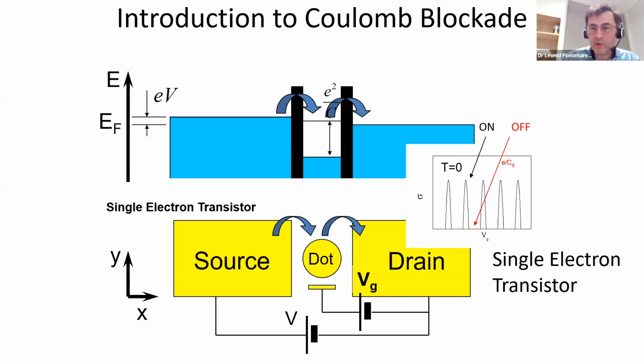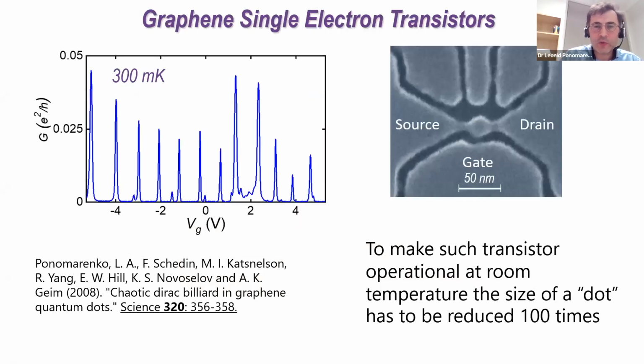It was a really, really hot topic in the 80s when these transistors were made of traditional semiconductors and metallic islands. They work only at low temperatures. So we have actually tried to do this with graphene, and we have succeeded. We made the device out of graphene. Instead of tunneling barriers, we just made a constriction. That's an old paper, 2008. But we indeed observed the Coulomb blockade, and we have shown that such a device works. Unfortunately, it works, as you can see, at a temperature of 300 millikelvin. In order to make it work at room temperature, we would have to decrease the dot by about 100 times, which is not possible with current methods of lithography.